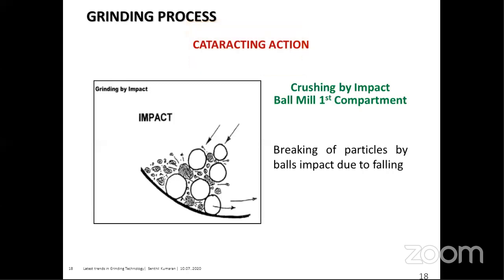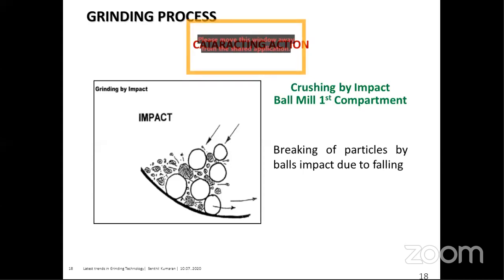In the grinding process, the first compartment grinds by impact. As I said, it uses the larger grinding media, like the 90, 80, 70, 60 mm. These balls break the particles by impact due to falling. The ball mill rotates, the balls are lifted up to some level, and then the lifted ball falls on the material, impacts it, and reduces the size.